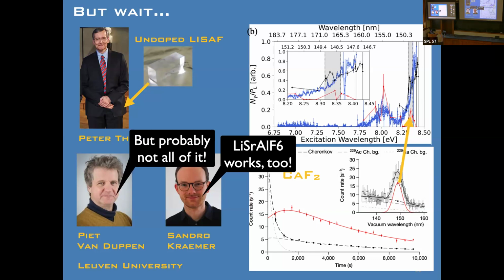But probably not all of it. And this was really the key. We had thought, if it's quenched, maybe some aren't quenched, but maybe it's a part per million or a part per billion. You have no right to expect it to be half quenched, right? What they saw was maybe, it's hard to get accurate numbers, but maybe 10% of it is emitting and 90% might be quenched.